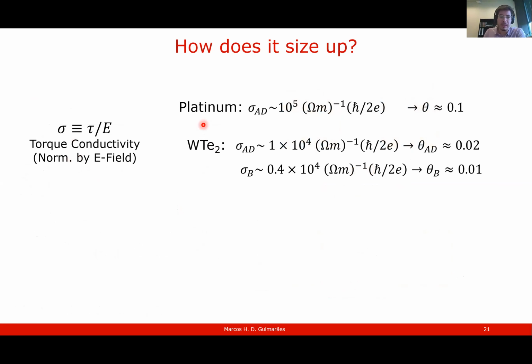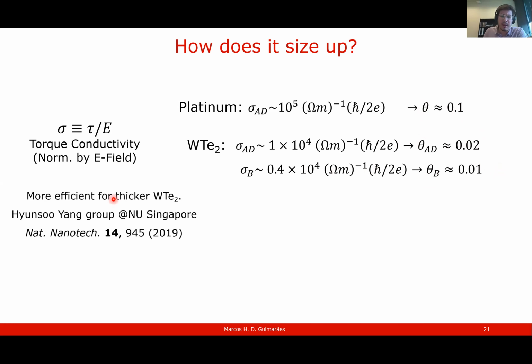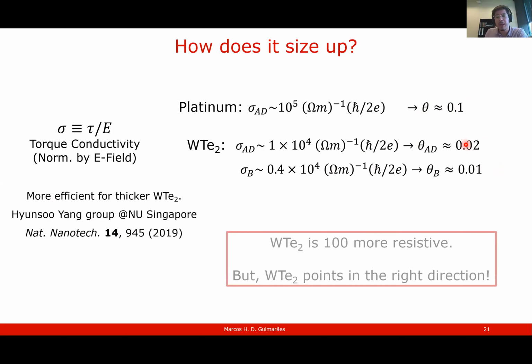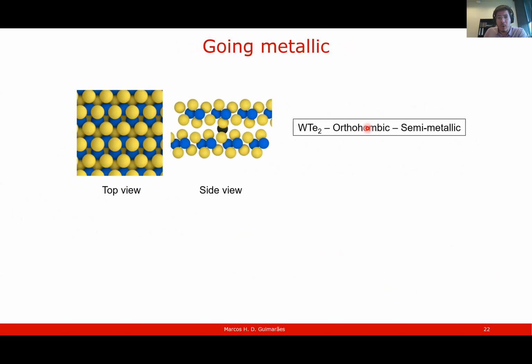But how does it size up? So we have platinum there that has a spin Hall efficiency of about 10%. And tungsten ditelluride for these special torques, the efficiency is actually pretty low, about 1%. And the spin Hall-like torque, so the same symmetry as the platinum, has about 2%. So it's pretty low. The Yang group in Singapore found out that you get more efficient torques for thicker tungsten ditelluride and can get closer to platinum. But one of the reasons why the torques are a little bit inefficient is because tungsten ditelluride is very resistive. It's a semi-metal, but it points in the right direction, that we can control the torques with symmetries of the crystal. So what happens if we go to a metallic system?